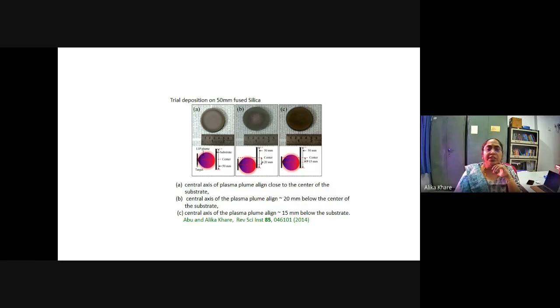So this location has to be optimized, and then once we optimize the location, we brought it slightly more closer to the center of the target, and then we could see uniform deposition. It was completely reflecting and completely opaque, with uniform deposition.